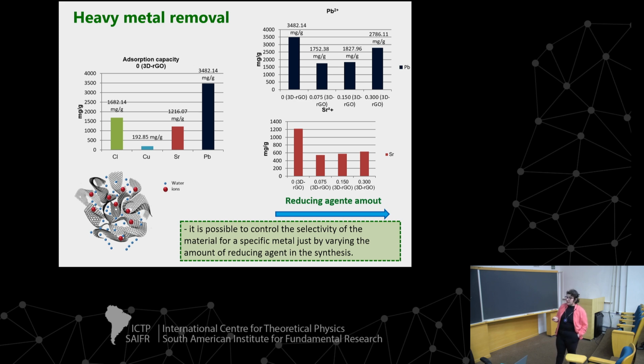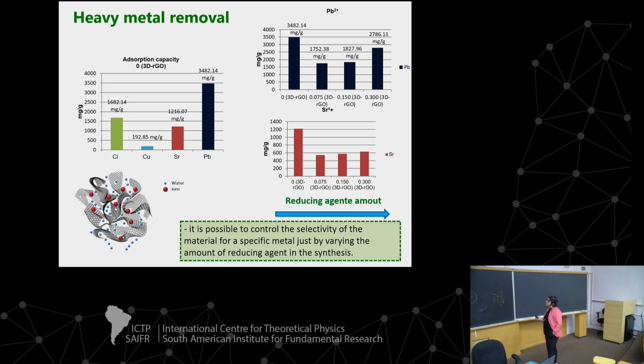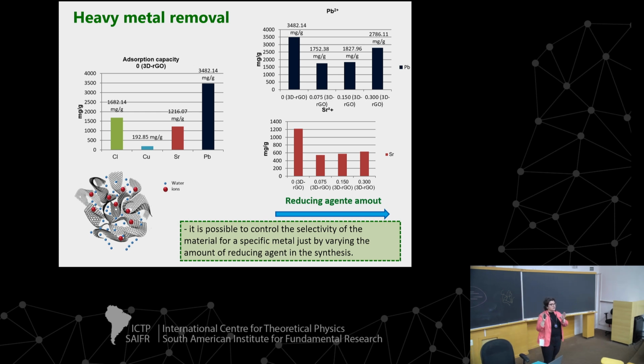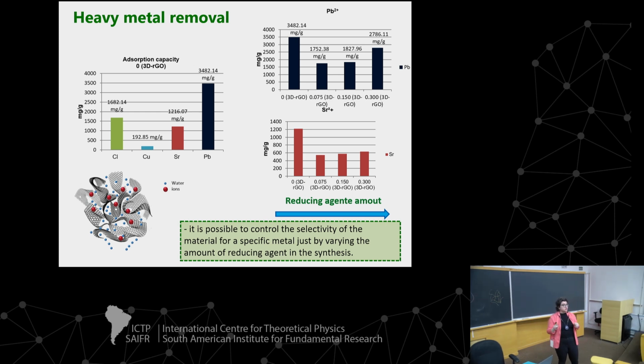There's no linear behavior. But we saw, again, it's possible to control the selectivity of the materials for a specific metal. So if we have a contamination with strontium, I can choose the less oxidized materials. If you have a contamination with plumbum, I can use the more reduced, for example. So I can design the material for a specific environmental problem.